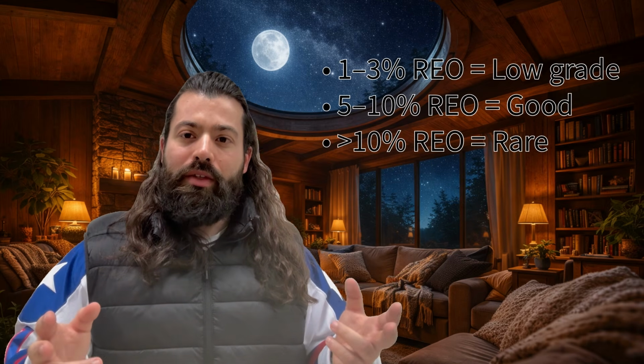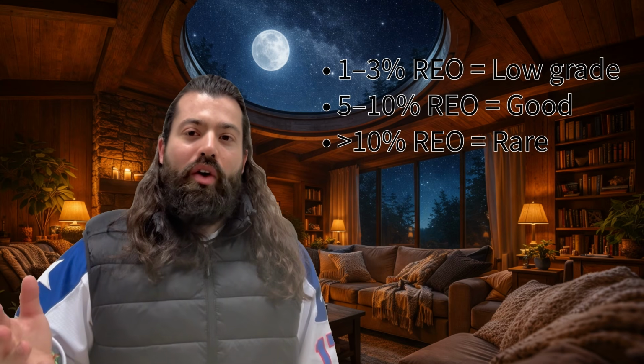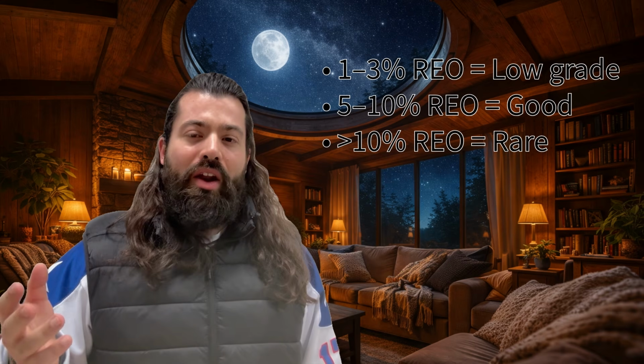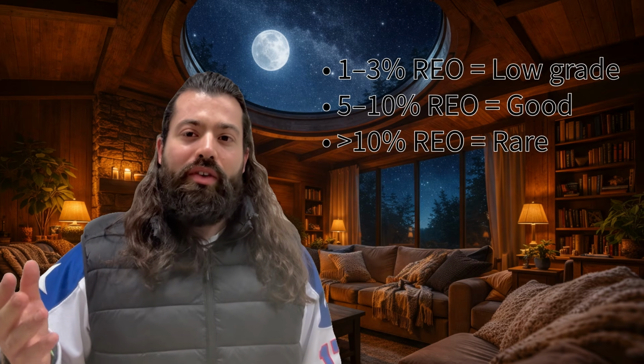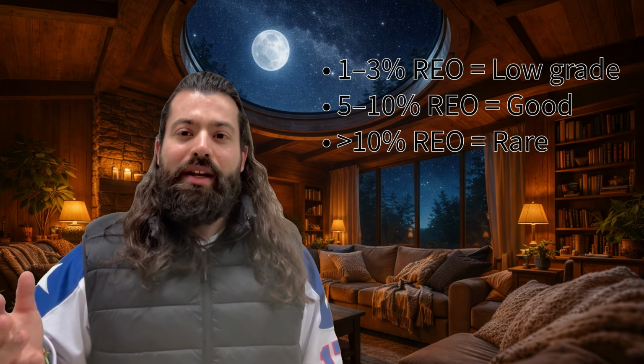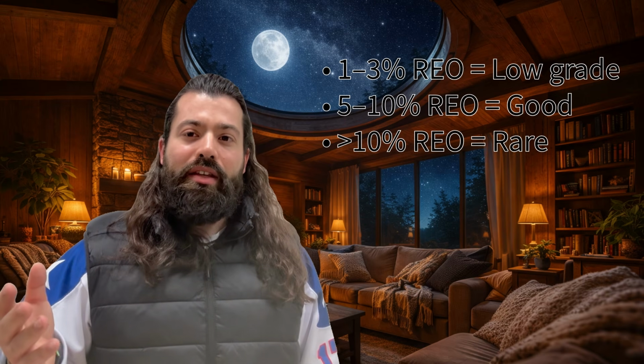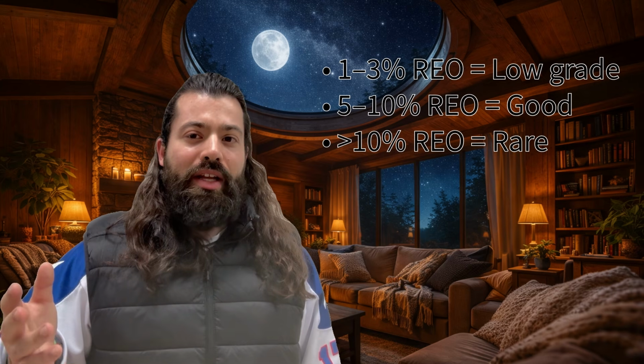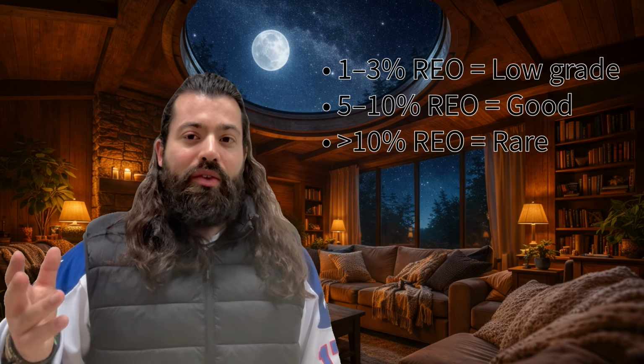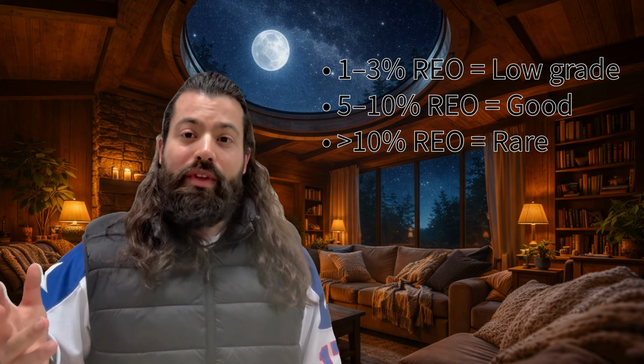As we said in episode 2, we don't magically find concentrations of rare earth metals underground. They're embedded in rocks and minerals. Some of the minerals are called bastnäsite, monazite, and xenotime. For the first step, we need to mine the ore out of the earth. A typical low-grade rare earth oxide ore contains 1 to 3% rare earth oxide. A good grade would contain 5 to 10% rare earth oxide, and a very good grade would contain above 10%.